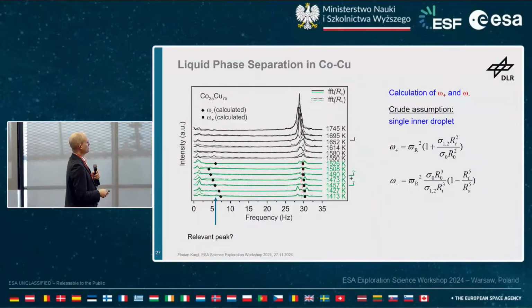And you see this Rayleigh peak is changing in the undercooled liquid state. The green data here is undercooled liquid. And you seem to develop an additional peak here, and this main Rayleigh peak seems to disappear. Of course, you can ask the question, where's the relevant omega minus peak? The black data here is a calculation from a simple model, assuming that you have droplet in droplet effectively. And you end up with these data points here, and then you have to search where the relevant peak is. You might ask if this perhaps might be the relevant peak, but if you then do a calculation, you get interfacial tension values that are pretty much off what you would expect.